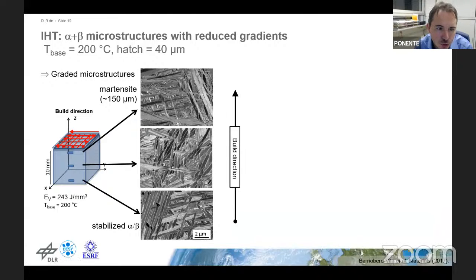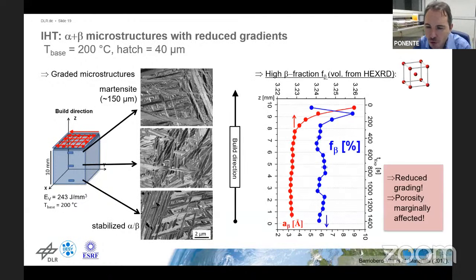And that's simply due to the fact that the bottom layers have seen more laser passes from top layers that have been added to the specimen, whereas the top layers only have seen a few, so only a few times laser energy input in the material. So this is something you have to always keep in mind in the material with SLM or LPBF. The material that later on will be generated in a component doesn't have to be homogeneous.